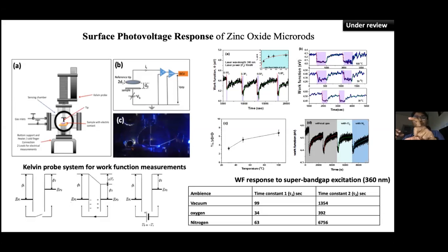Now the band gap of zinc oxide is somewhat 3.3 electron volt, and if you shine on it a light which has higher energy than 3.3 electron volt, you are causing super band gap excitation. That means you are basically exciting one of the electrons from the bound state to the conduction band. So you have effectively generated photo carriers, that is a hole and an electron pair. So this contributes to the current.